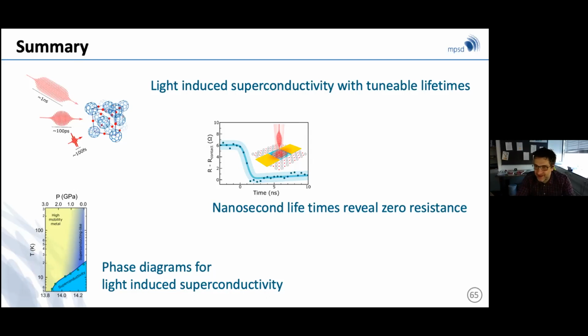This is now a complete extrapolation. Let's imagine that you are dealing with a bosonic system in which pairs are formed, so let's say the energy scale for the pairing is T star, some high scale, and so T mean field is infinity, and then in reality, in equilibrium, you have an order-disorder transition for the phase, which you're then synchronizing by some periodic drive. Then I would argue that the phase rigidity is the shortest time scale that you can sync those things up. And now let's take the opposite view. Let's go to an extreme BCS world in which the phase is basically an infinite energy scale, and now what you're doing is making pairs. Then I would say that 2 delta is the faster time scale that you can form them.